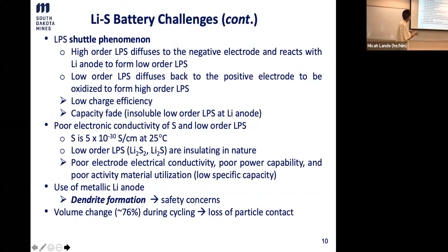So this is a phenomenon called the shuttle mechanism. What it is, is that the higher order polysulfide diffuses to the negative electrode and then reacts with the lithium anode to form the low order polysulfide. And then they won't stay there, and they actually shuttle back to the positive electrode.